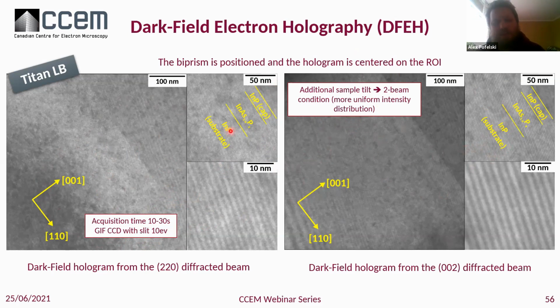So this is on the 220, there is no deformation. On the 002, if you look well, you might see that the fringes here change the spacing and a little bit of their orientation. This is the indication that there is a deformation field.